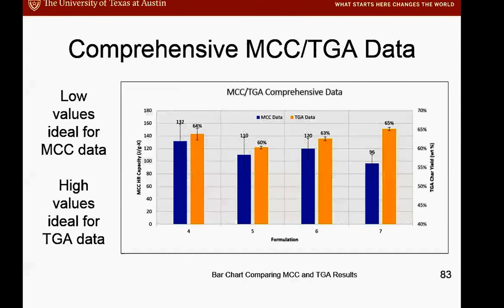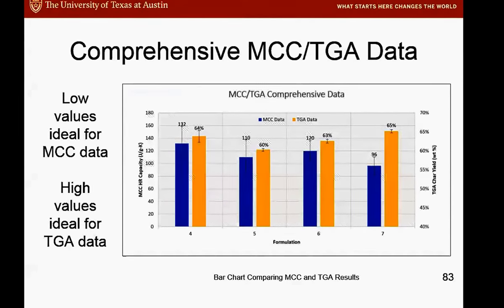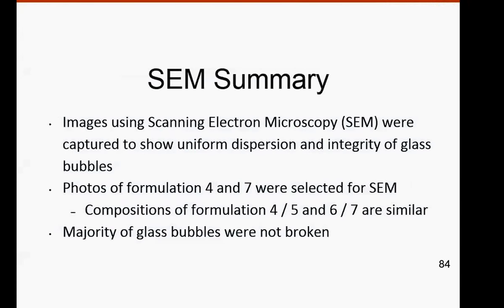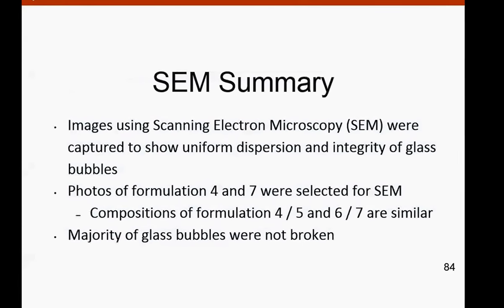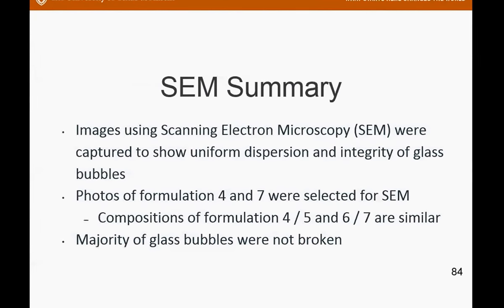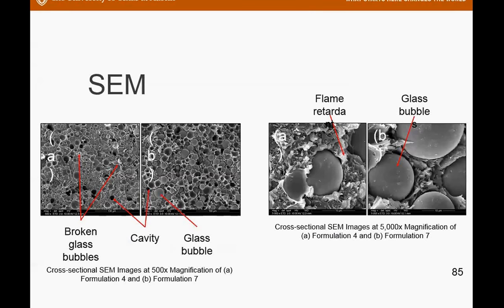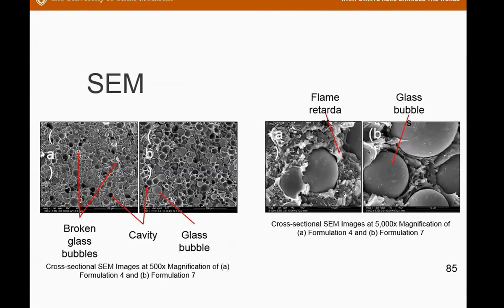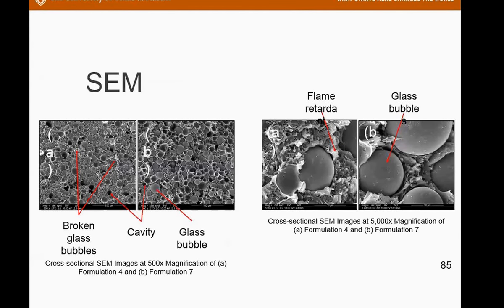Okay, these are all the data that we collected: lower values for MCC and high values for char yield. And we also check the dispersion and also the mechanism using SEM, and we did all these, and we found out certain things. We're not sure if we use shrinkage extrusion, are we going to crush all these micro balloons? Well, we actually did check, and we found that only a very small amount of these glass balloons were crushed. The majority of them still remain intact, because in shrinkage extrusion you have very high shear, which is going to break some of these hollow balloons.